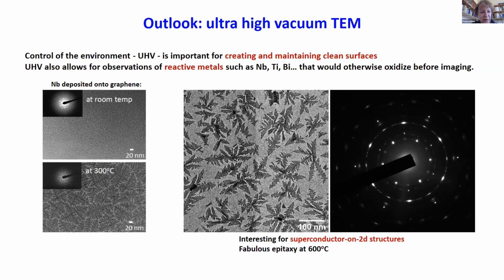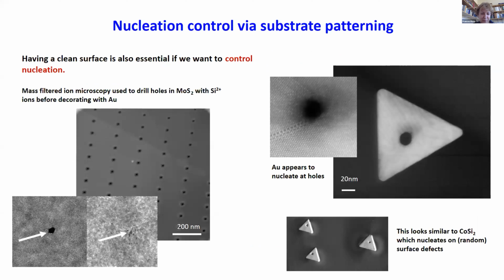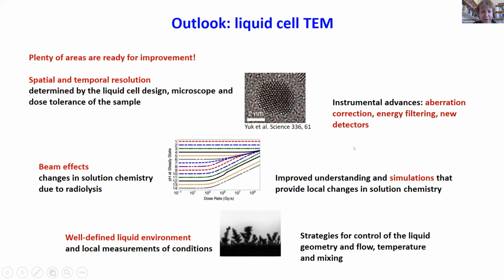But if you also have the ultra-high vacuum environment and the good control of the substrate, then this opens up other possibilities. If there are no random locations where things nucleate, then you can pattern nucleation sites, and those will be the only places that are good for nucleation. So we can envisage experiments where we pattern our 2D material with maybe a FIB or maybe the electron beam itself, and then do a nucleation experiment and control the position of the islands that grow.